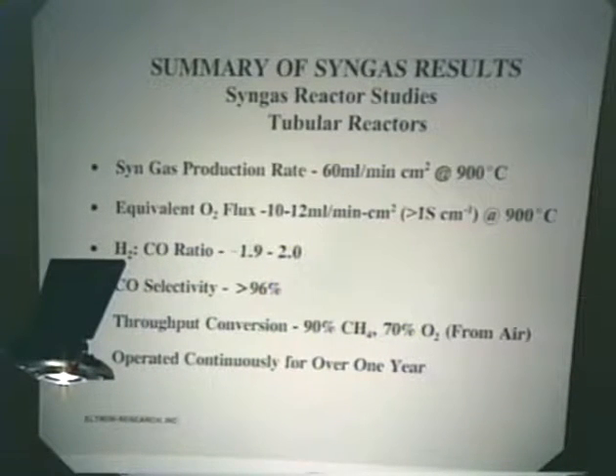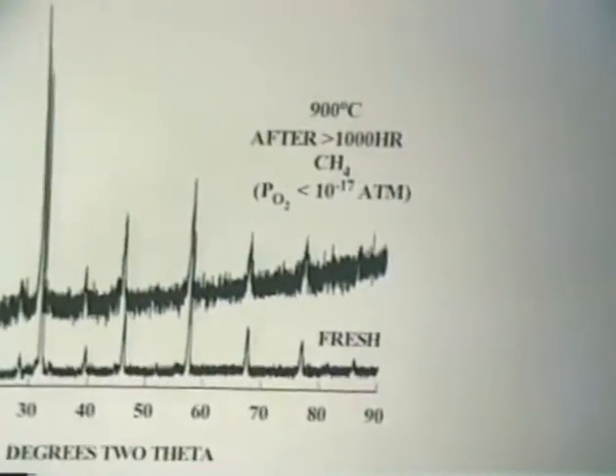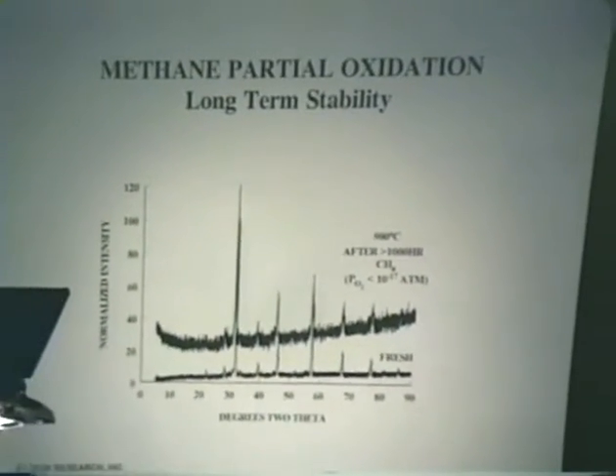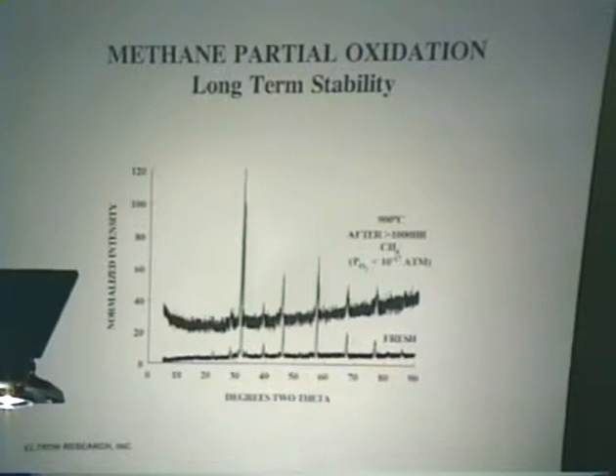And most significantly, we have in fact operated these devices continuously for 1 year, which we were very impressed with ourselves, quite surprised. This just shows some of the very early evidence that we had stability. We had some devices that had operated in excess of 1,000 hours, and for some reason we relocated our facilities within Boulder, and we took these samples down, and we found that the X-ray diffraction patterns were essentially identical. These were devices that had operated in excess of 1,000 hours with a considerable oxygen partial pressure gradient across the devices, and that's kind of a yardstick for stability with these materials. If you can operate a device with something like a 10 to the minus 17 oxygen partial pressure, that's certainly indicative of considerable stability.